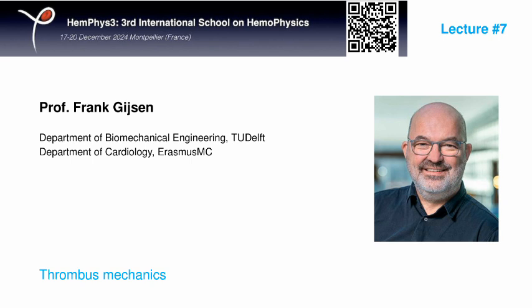One thing that we are going to try, especially with the photon counting CT scanner, is to follow, under different compressions, the permeability of the structure for clinical contrast agents, under a slight pressure gradient. It's still a very simple approach. I don't know if it gives us the answer. You would expect it to, but it's much more complex than it seems.